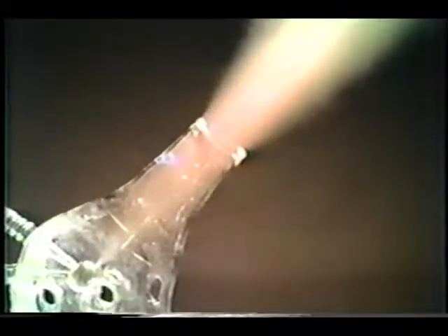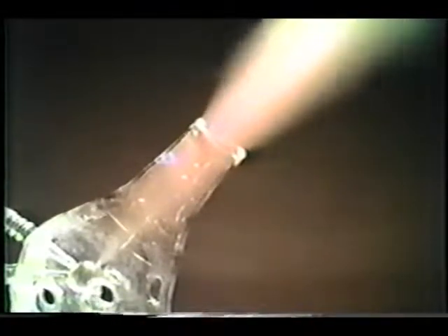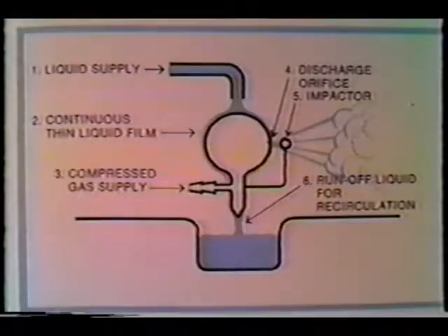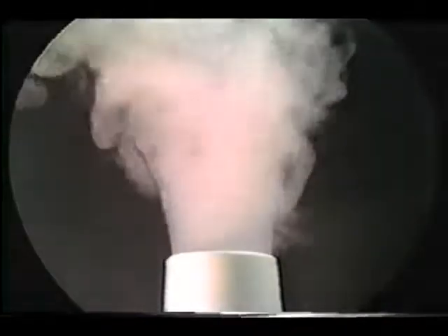In applications where somewhat smaller liquid particles are desired, down to 5 microns, the basic spray can be passed through a conical shroud. When ultrafine particles are required, a spherical impactor is placed in front of the discharge orifice. This provides a second stage of liquid particle breakup, as the basic spray is forcefully impelled against the impactor. The smoke-like fog that is generated by this technique is comprised of particles with a mass median diameter of less than 2 microns.